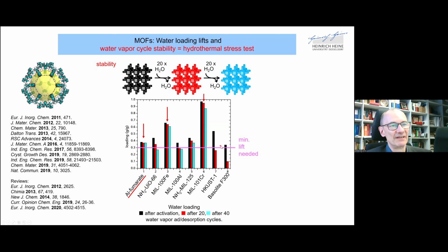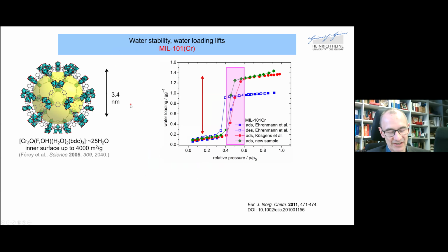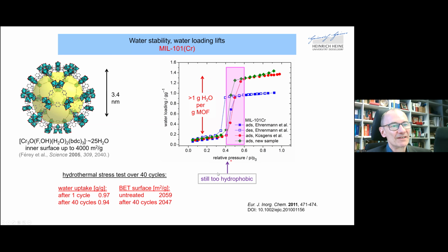So all of them meet this 0.3 gram per gram target. And the other MOFs, which you also see here, either show a large degradation, or move below this target line. So MIL-101, I showed you the structure early on, has this highly porous network with a large surface area of up to 4,000 square meters per gram, and it can take up its own mass in water. So there is a loading of over 1 gram of water per gram of MOF. The only disadvantage is it's too hydrophobic. So the uptake occurs above 0.4 relative pressure of water, and that is above the threshold, which I noted, which would be 0.35. Otherwise, it has good stability, and it did not degrade over the 40 cycles which we measured.